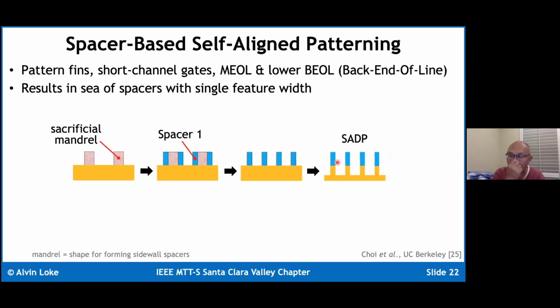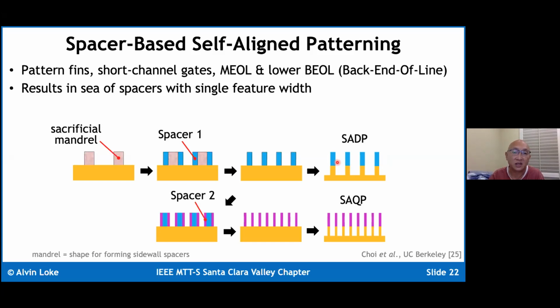So in order to get those even finer fin pitches, we repeat this madness again, where we use our spacer ones as the mandrel for growing a set of spacer twos around. So now you have twice as many spacer twos as spacer ones, or 4 times as many spacer twos as your original mandrel. And so now you're getting 4 times as many fins as you have mandrels. This technique would be used to get you down to the sub 30 nanometer, or actually sub 40 nanometer fin pitch.